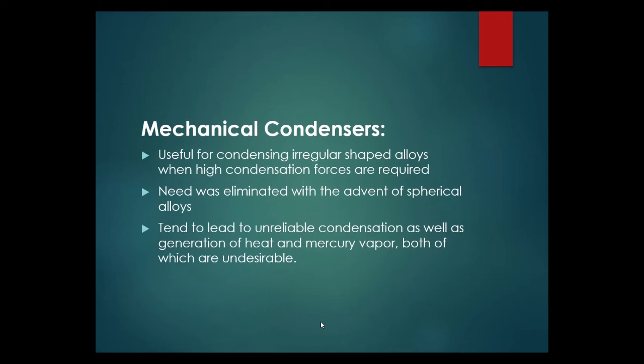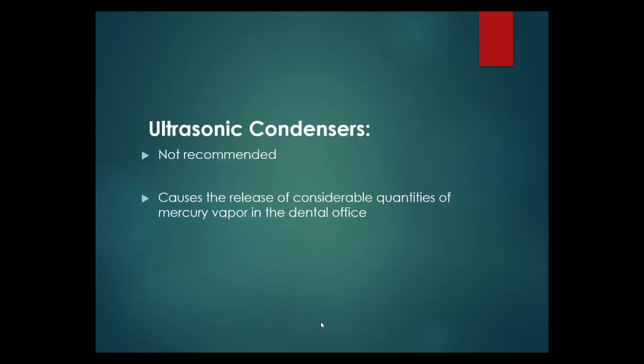Mechanical condensers are useful for condensing irregular-shaped alloys when high condensation forces are required; however, this need was eliminated with the advent of spherical alloys. They tend to lead to unreliable condensation as well as generation of heat and mercury vapour, both of which are undesirable. Ultrasonic condensers are not recommended anymore because they cause the release of considerable quantities of mercury vapour in the dental office.